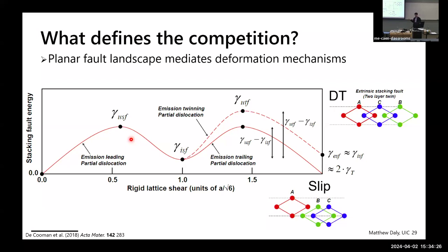Basically what this is showing is the x-axis is shearing of a lattice, and the y-axis is excess energy introduced into the system due to this process. And as you go over the minimums and maximums of these two curves, the dashed line being for twinning and the solid line being for slip, you're seeing the relative energy penalties that you're introducing into a material to introduce these defect structures. And so really,